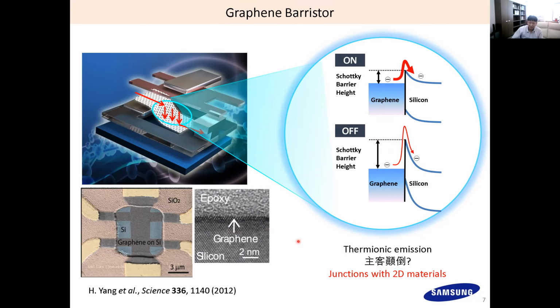And here, in Korea, we use ancient Chinese letters. This means this graphene here looks quite thick, but it is only 3 angstrom in thickness. And you see the depletion width is on the order of 100 nanometers. So this 3 angstrom, 0.3 nanometer material controls this 100 nanometer thing. This is why I used this term. And here we don't see any silicon native oxide. We see graphene very well.